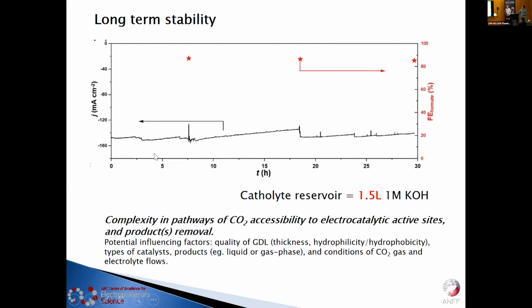Imagine if you want to do long-term tests, or in a real application, we need to run for a long time, like in this case, 30 hours. You can see we have to use 1.5 liters of KOH. So that means the use of KOH, in principle, is not a really efficient way, although you can get a high current density. And of course, there are other factors, like the quality of the gas diffusion layers and the catalyst, but still, fundamentally, the electrolyte plays a key role in this stability effect.